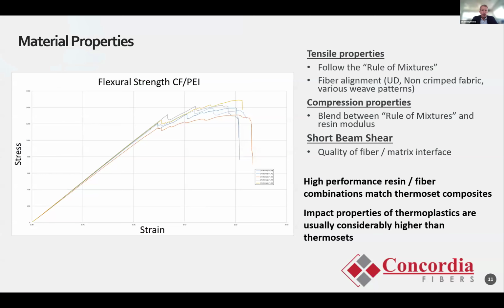So lastly, I want to talk about material properties. Here we depict some testing for flexural strength of a carbon fiber PEI combination of a unidirectional. The first thing you can see is a fairly linear, consistent elastic zone on the left-hand side of the curve, and then a little bit more noise on the end of the curves, where maybe there are some secondary type failures taking place before the full failure.